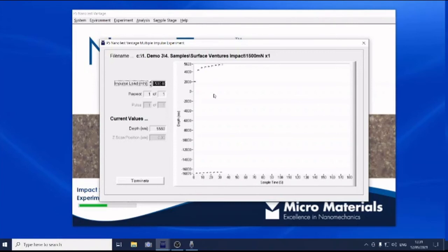Normally, a very, very abrupt failure would appear as a large change in depth between one impact event and the next. So depending on how sudden the failure is, the scale of the difference in terms of depth between one impact event and the next will change. So this sample is kind of somewhere in between a brittle and a more tough response. So there we've got a fairly significant increase in depth, and there we go. So this is the beginning of our impact failure. Okay, so there it goes.